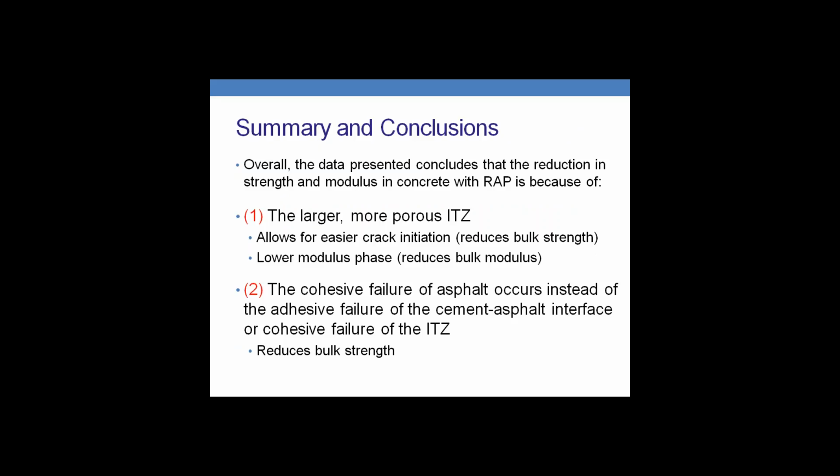So therefore, we're reducing the bulk strength a bit. It's also a lower modulus phase, so it's more porous, so it's more compliant, and now it's larger. And thus, overall, the bulk modulus of the concrete is being reduced. And in my thesis, which I didn't present here, we did some models and confirmed that it is affecting the modulus that much.